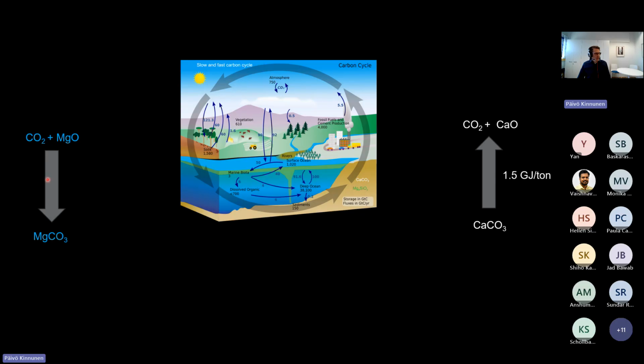And unfortunately, you cannot do this. Well, let's say you can do that with calcium oxide. It's just that calcium is present as calcium carbonate in the crust. So if you have a large-scale source of calcium oxide, in its history, it has been first calcium carbonate, and then it's been decarbonated. So this is why taking any waste calcium oxide is very important that we do that, but it's not actually doing what we think it does.